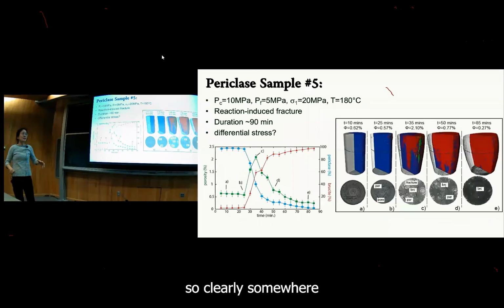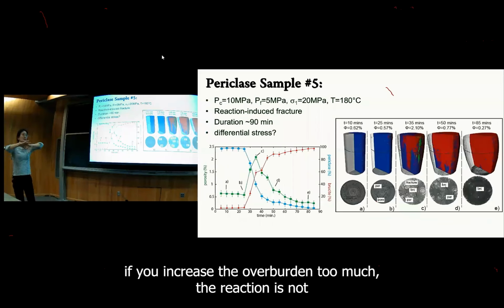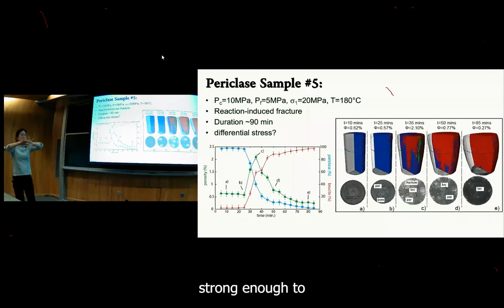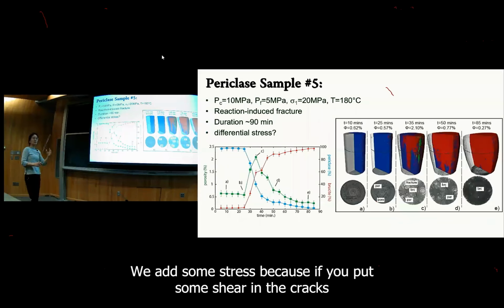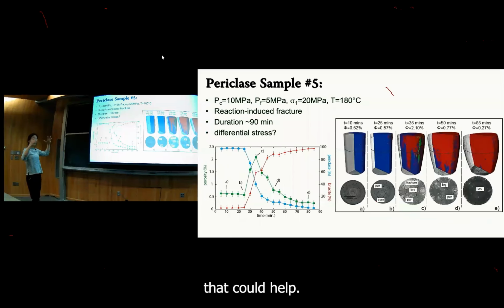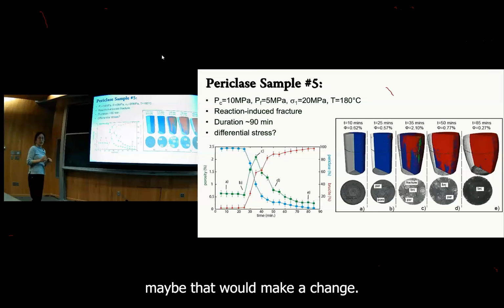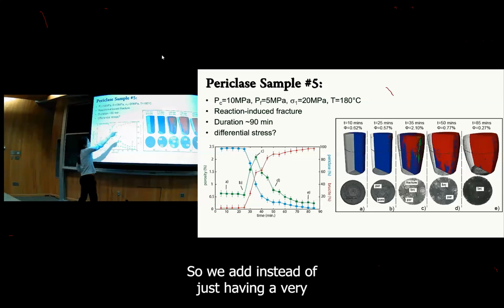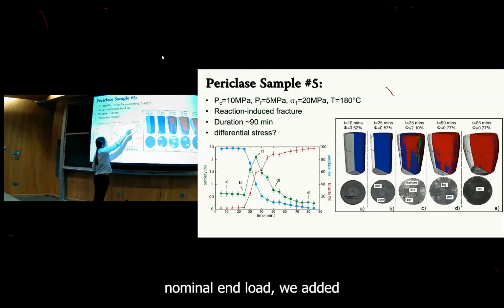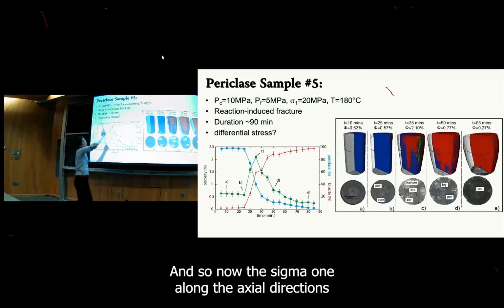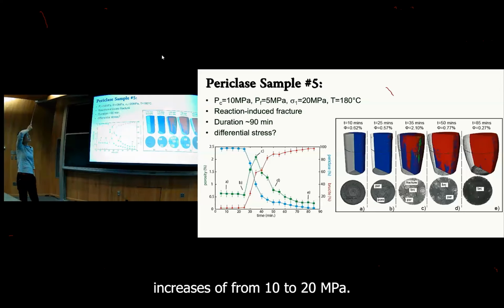Then I said, oh, so clearly somewhere, if you increase the overburden too much, the reaction is not strong enough to break the rock. The overburden was too high. How about we add some stress? Because if you put some shear in these cracks, that could help it either open or slide, or maybe that will make a change. So instead of just having a very nominal end load, we added an axial differential stress.